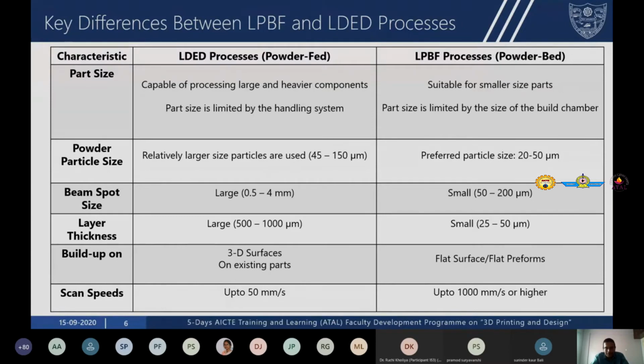One of the big advantages of the directed energy deposition process is that you can deposit on an existing 3D surface or an existing part. Whereas in the case of powder bed, since you have to spread the powder on a bed, you need a flat surface or a flat preform. The scan speeds in directed energy deposition are much lower compared to powder bed fusion. The maximum scan speed seen today is about 50 millimeter per second, whereas in powder bed fusion you can go up to 1000 mm per second. So there are a couple of important takeaways from this slide. One is that the powder particle size in powder bed fusion is much smaller, the layer thickness is much smaller, and the scan speeds are much higher when compared to the directed energy deposition or the LDED process.